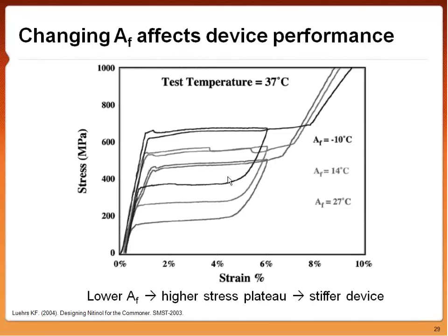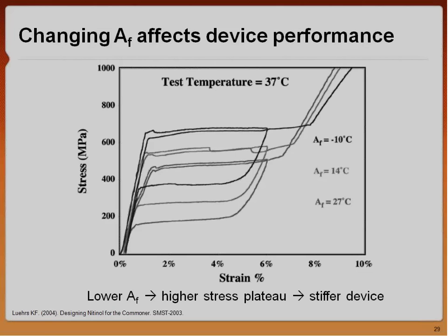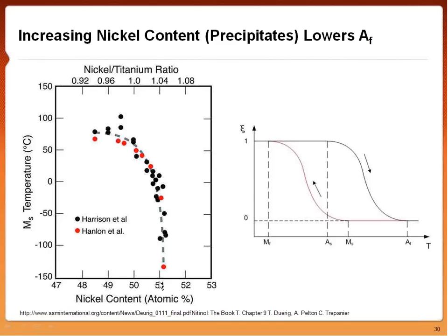When we look at this graph over here by Harrison et al., it basically says to us that as a function of nickel content, the more nickel we have in our matrix, the more suppressed our martensite start temperature is. And the less nickel we have in our matrix, the higher our martensite start temperature is. Again, we can still think of this in terms of austenite start and finish temperatures as well. You just have to think about which curve you're on, the heating curve or the cooling curve.